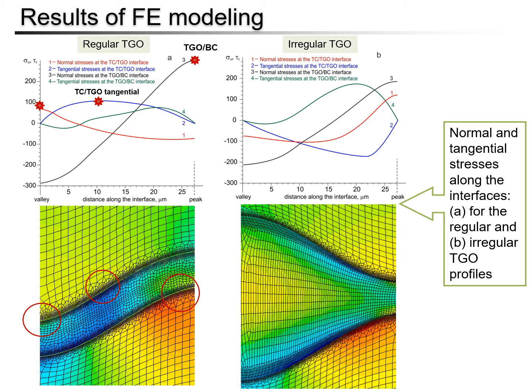where corresponding normal and tangential stresses are well above the critical values. In the case of irregular TGO, the stresses at both interfaces exhibit a similar distribution pattern. However, the maximum normal stress located at the TGO-BC interfacial peak does not exceed 200 megapascal. Mode 1 debonding initiation was not observed for this case. The debonding due to tangential contact stresses is most likely to occur at the middle of TC-TGO and TGO-BC interface.